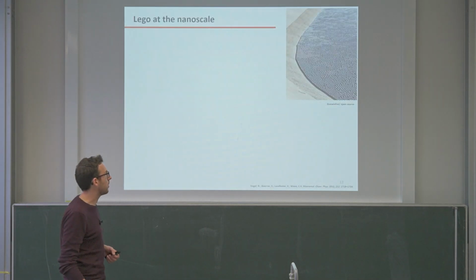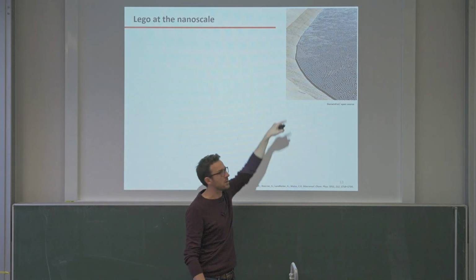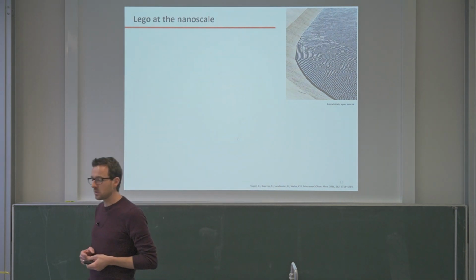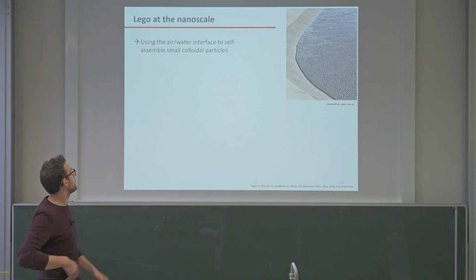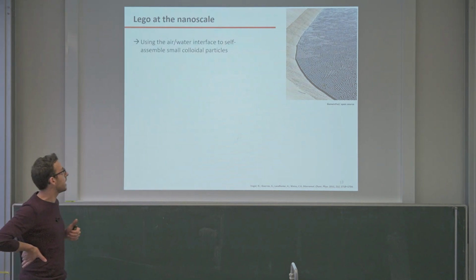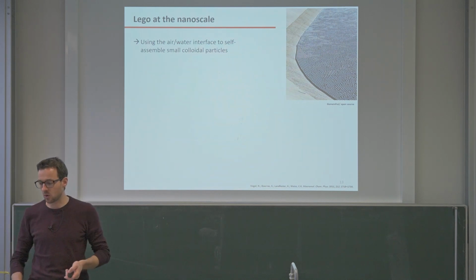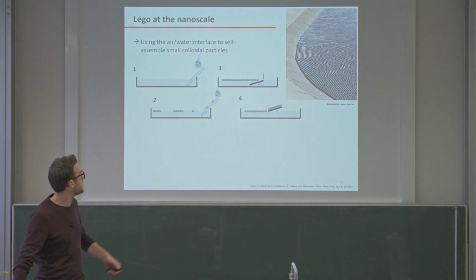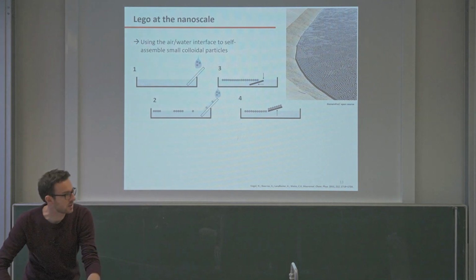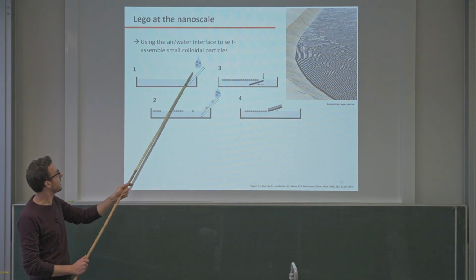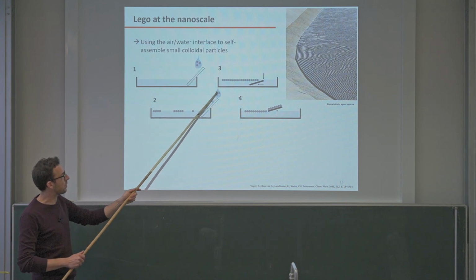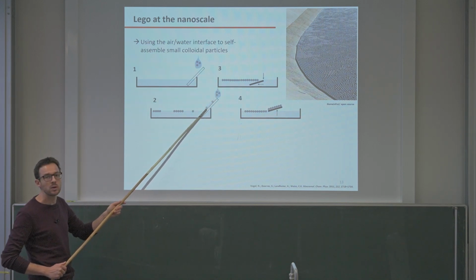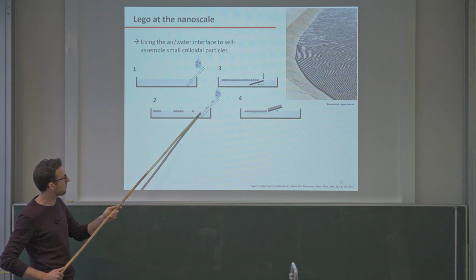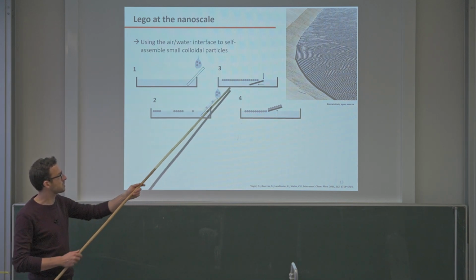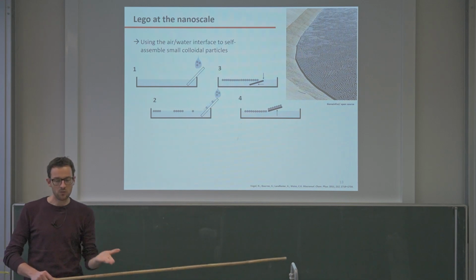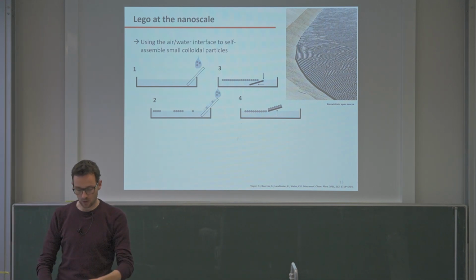So you see this video runs for a long time. After some time, this is the typical close packing of spheres in 2 dimensions. And what we do here is the same thing. We exploit the air-water interface as a template to assemble the colloidal particles. How do we do this? You see we have a slide as well, or an inclined plane. In our case, we use a glass slide. This is a normal beaker. Then we let our colloidal dispersion drop down here. They slide down this ramp, get in contact with the water, assemble into these close packed layers, and then we simply take a substrate, fish them out, leave them for drying, and we are done.